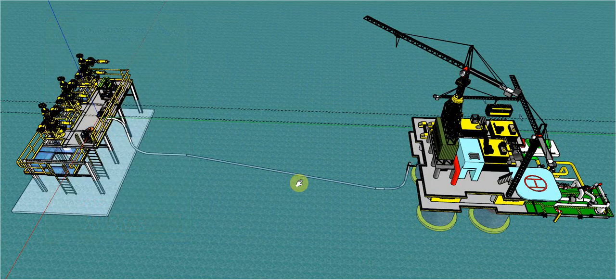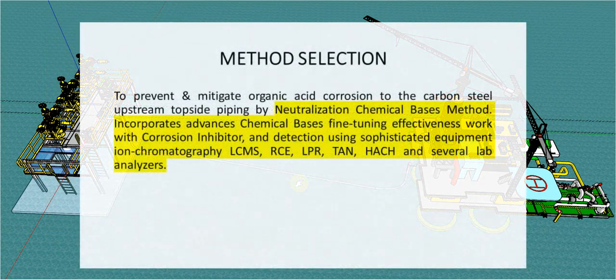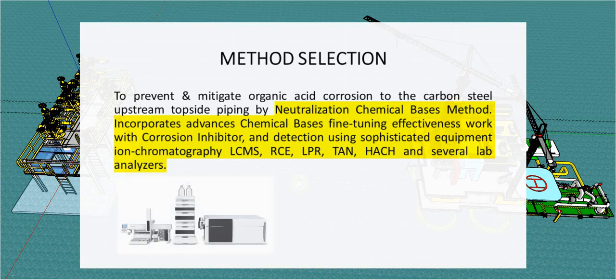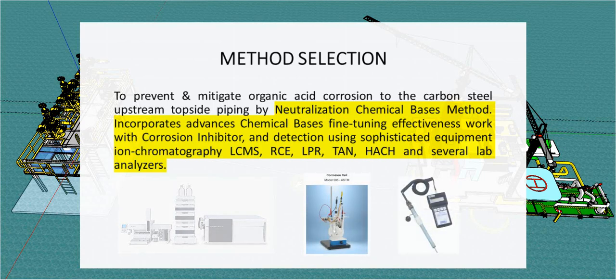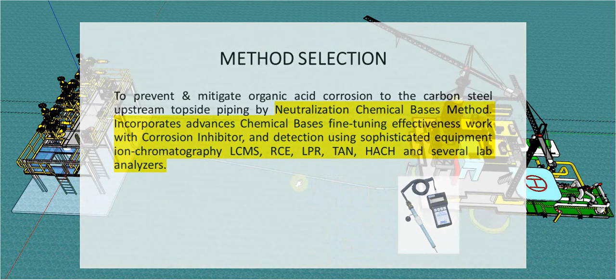My TC11 proposal summary is to prevent and mitigate organic acid corrosion to carbon steel upstream topside piping by a neutralization chemical-based method. This method incorporates advanced fine-tuning of chemical selection effectiveness and detection using sophisticated equipment: ion chromatography, liquid chromatography mass spectroscopy or LCMS, rotary cylinder electrode or RCE, linear polarization resistance LPR, total acid number TAN, and several lab analyzers.